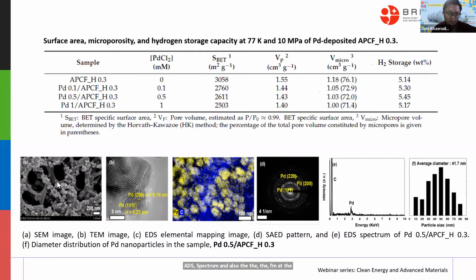So from the SEM also, it's clear. The pore diameter and the morphology are very beautiful for this kind of sample with the name PD 0.5, APCFH 0.3. And the particle size is about 41.7 nano on average diameter. The range is from 10 to 80 nano.